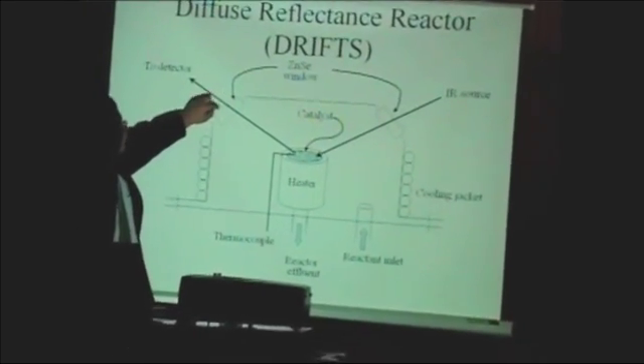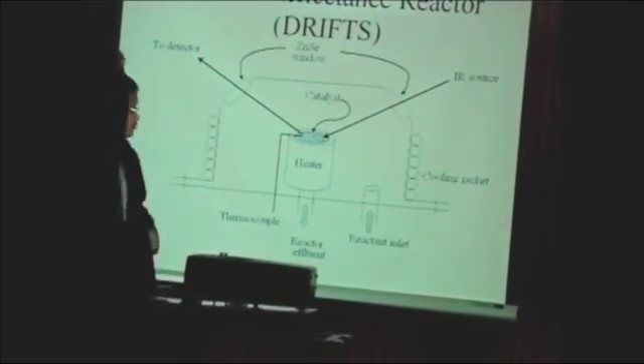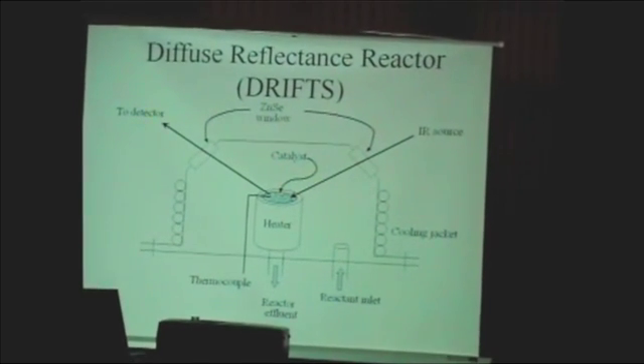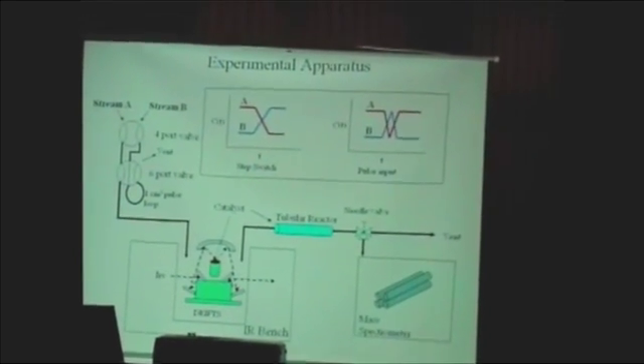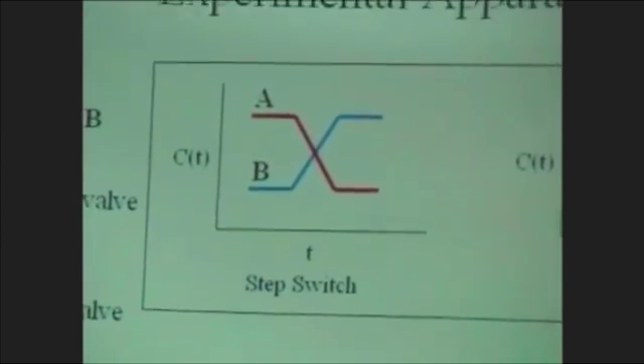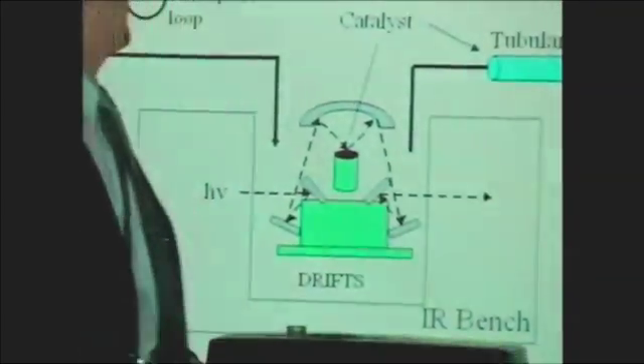And a lot of hydrocarbon or heavy species sometimes can condense on the glass wall here. So you can put about 20 milligrams of catalyst in the reactor here. In our study, we put 20 milligrams of the catalyst in this reactor, and we also put about 80 milligrams of catalyst in a quartz reactor, so that we can produce enough product to be detected by mass spectrometer or gas chromatograph.